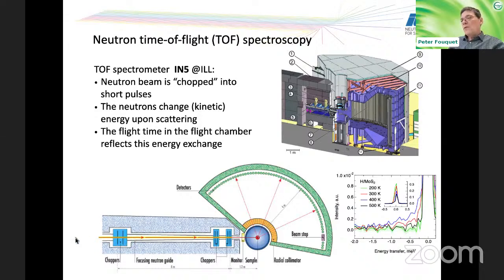In that spectroscopy, you have a white beam of cold neutrons that come from a liquid hydrogen source close to the reactor, and then this beam is chopped into little pulses with so-called chopper disks, which are blades with holes in them, and they cut this neutron beam into pulses that fly through the instrument, hit the sample, and then you have a detection of the signal at the detectors all around. And you can see it here in a 3D print.